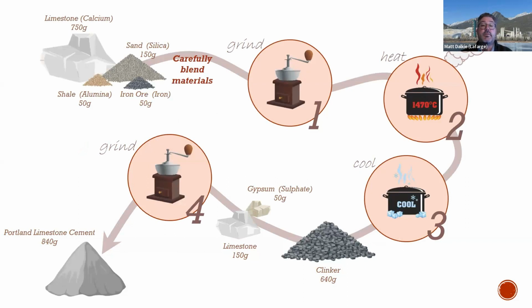If you know a little bit about chemistry, limestone in the top left-hand corner there is a source of calcium, and this type of calcium is calcium carbonate, so CaCO3. When we heat that up, that CO2 is driven off from that calcium carbonate to create calcium oxide or lime. So that's the first step of the cement manufacturing process. That's where the majority of the CO2 is released. About 60% of the CO2 associated with cement is released as part of that process.